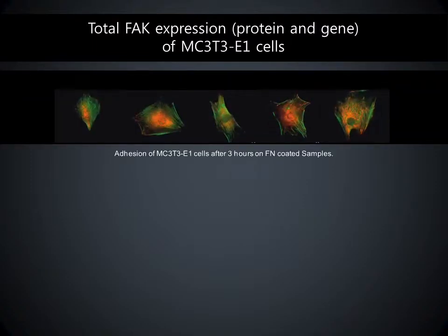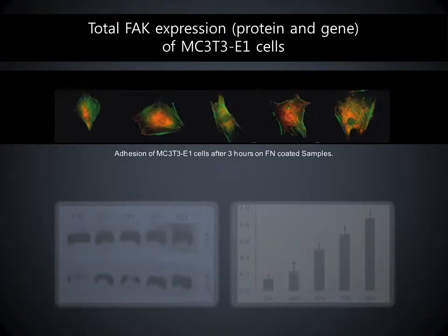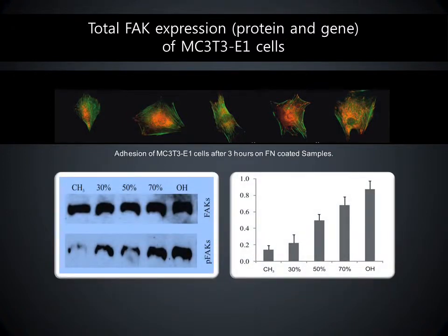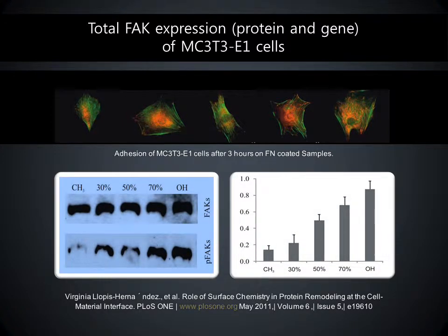Osteoblast cell line MC3T3-E1 was cultured for 3 hours for evaluation of cell activities upon the fibronectin films according to hydrophilicity of the surface. Total protein and gene expression of cells in fibronectin films upon the hydrophilic surface was higher than on the hydrophobic surface. In conclusion, the hydrophilic surface induced high osteoblast proliferation and activity.